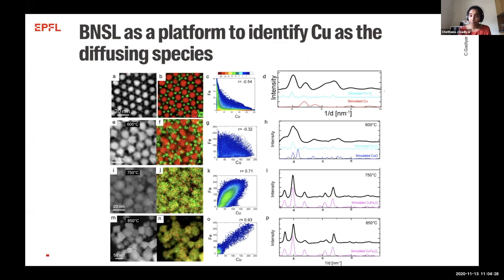So the next step that we did is to make a binary nanocrystal assembly. What you see here is that each of these big spheres is a copper nanocrystal, and it's always surrounded by six iron oxide nanocrystals around them. So we have this assembly of copper and iron oxide nanocrystals, and we studied them using electron microscopy-based studies.